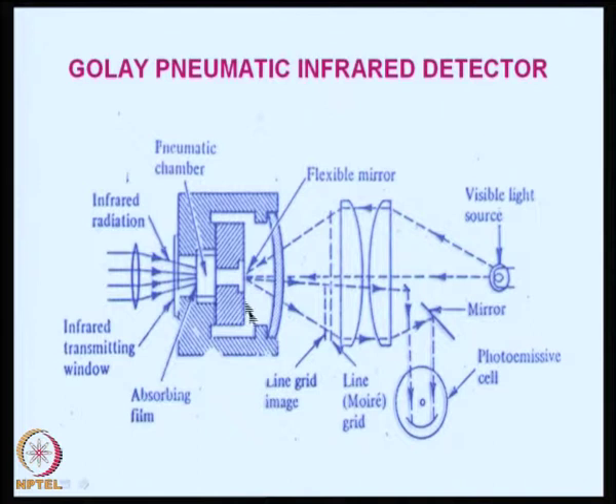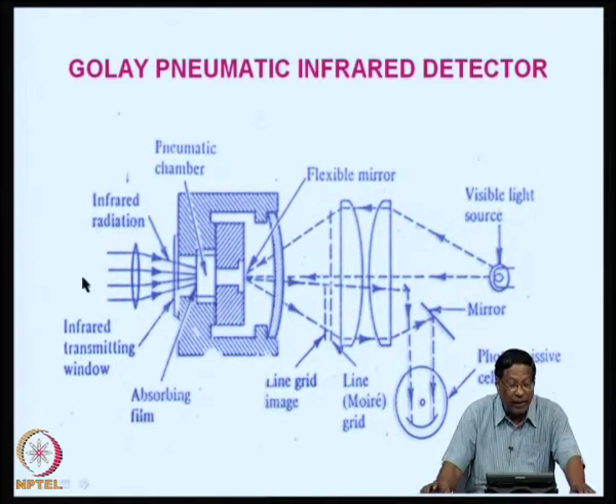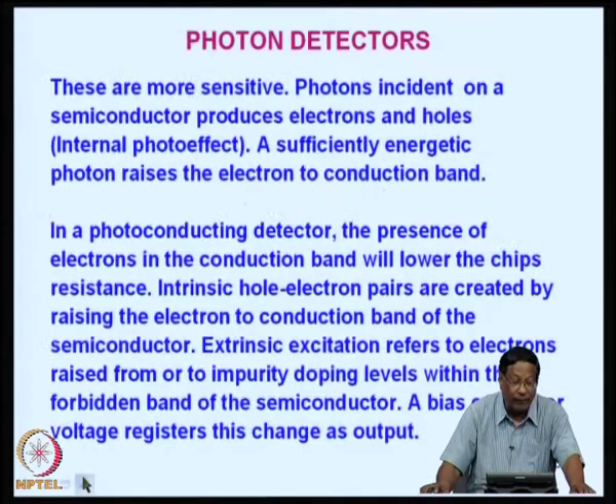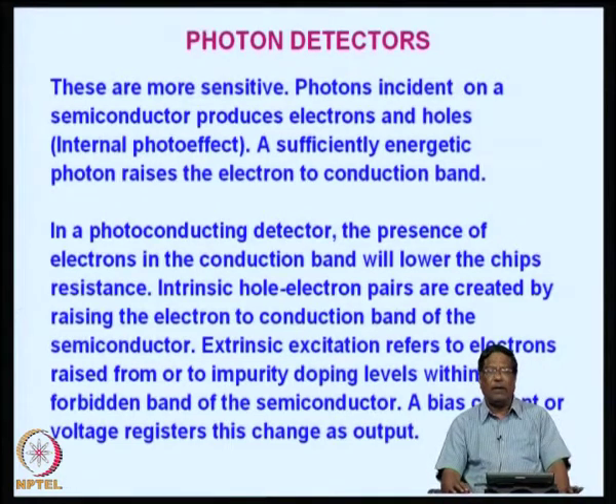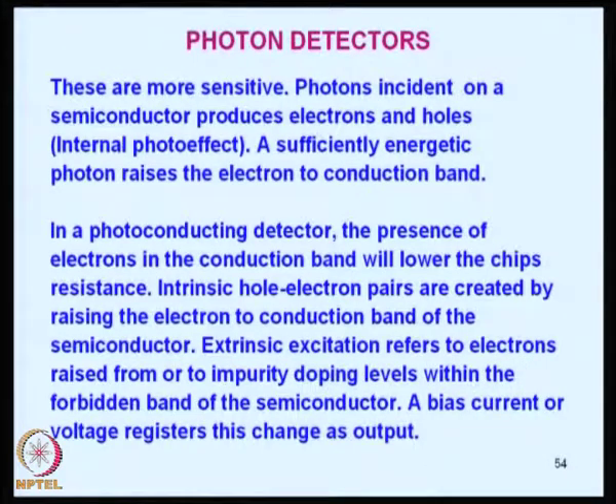So, this is the schematic figure of a Golay pneumatic infrared detector. You can see the pneumatic chamber is here, infrared radiation is coming from the back side from this region, and there is an infrared transmitting window, an essential part of all IR detectors, and there is an absorbing film, and this is a flexible mirror, and this one is the line grid image, and then you have a photoemissive cell through which the sample radiation is collected and the infrared radiation is monitored. So, you can study this in detail, and I can only say that Golay cell is the best as far as my experience also goes.